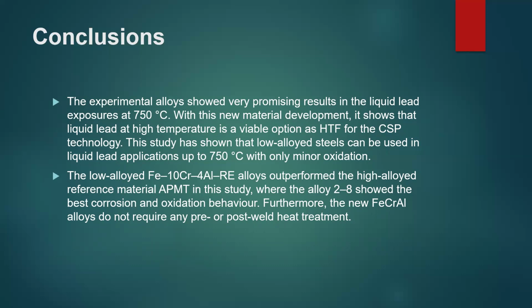The study has shown that low alloy steel can be used in liquid lead applications up to 750 degrees Celsius with only minor oxidation. Second, the low alloyed ferritic chromium aluminum RE alloys outperformed the high alloy reference material APMT, where alloy 2-8 showed the best corrosion and oxidation behavior.